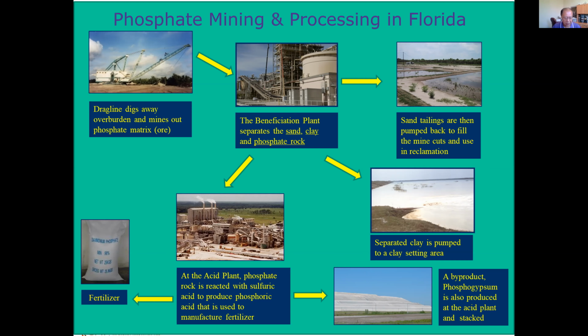So during this entire process, we generate waste clay, also called the slime or phosphate clay, which is pumped to a settling pond. The clay, as I pointed out, accounts for 1/3 of the phosphate ore. And also flotation tailings. Flotation is a fatty acid flotation, amine flotation, two-step flotation process. The flotation tailings is pumped to the mine cut for reclamation.